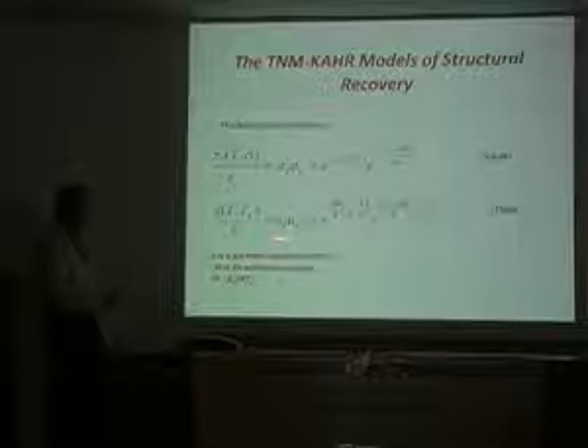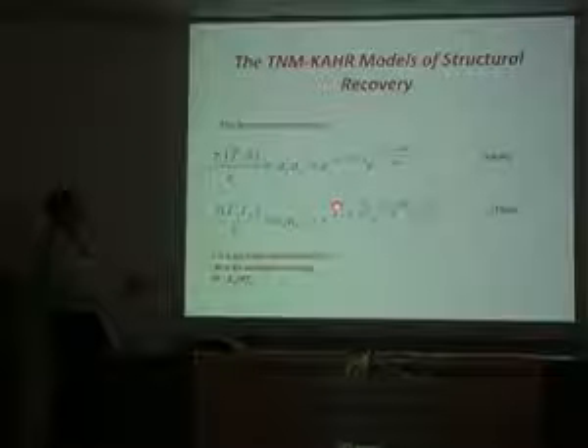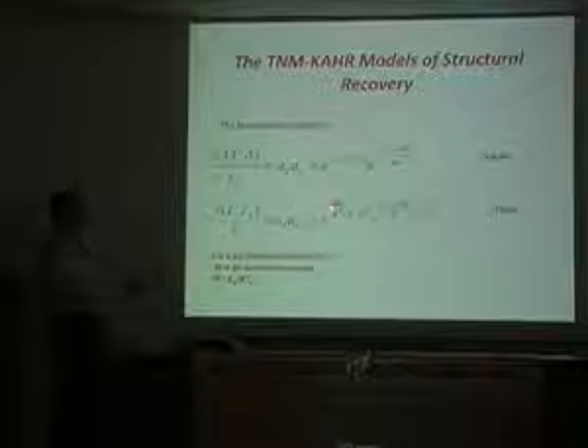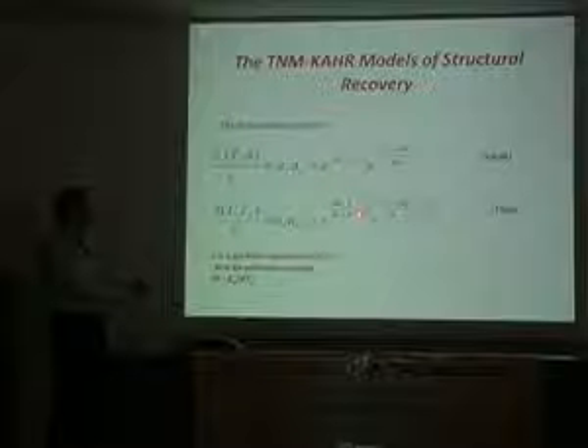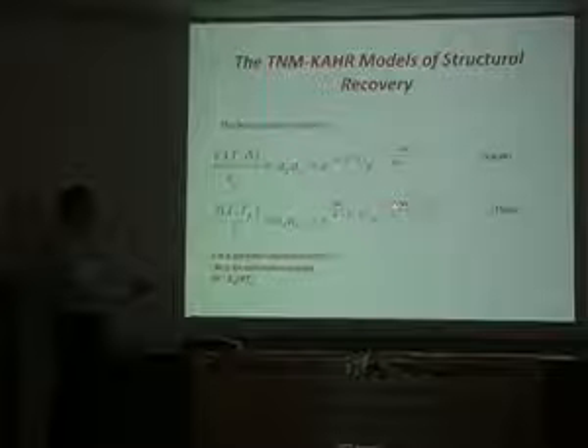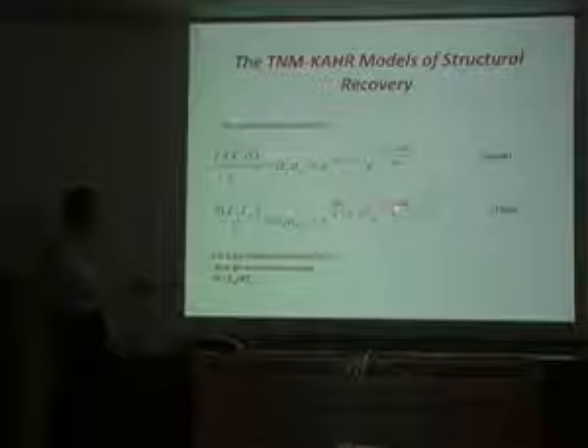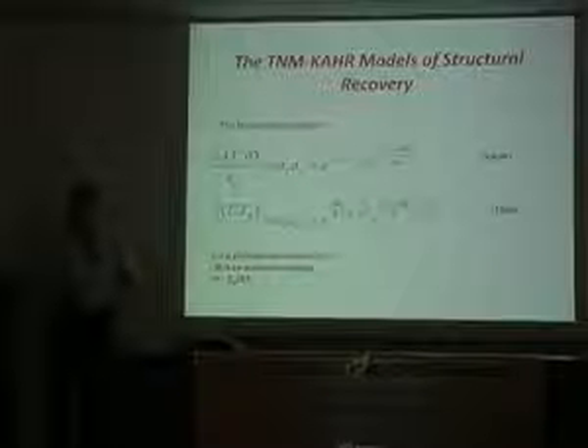In the case of the TNM model, they do it in terms of the fictive temperature, but then they use an activation energy, this delta H over R, and x partitions things, and it's clearer here: when x is 0, there's no temperature dependence, it's all fictive temperature dependence, and when it's 1, it's all temperature and no fictive temperature dependence, okay? No structure dependence.